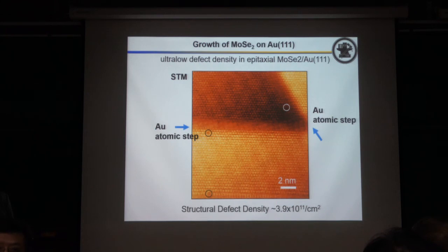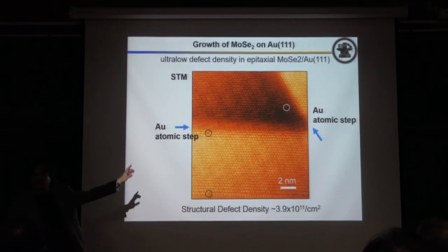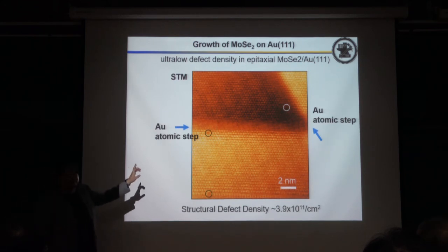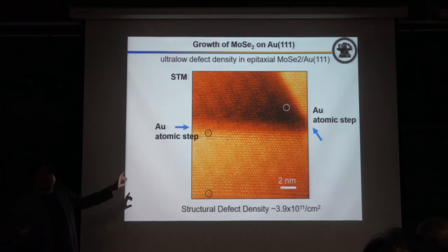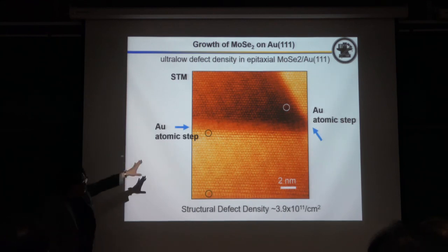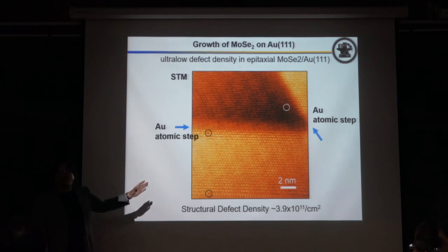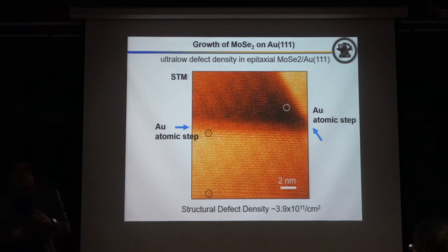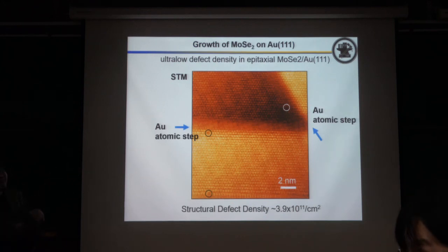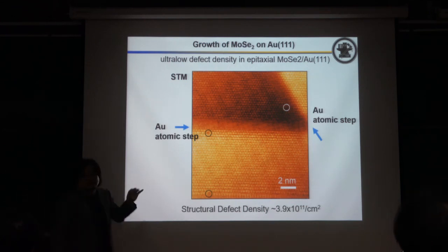I thought the typical defect is the vacancy, right? But actually, sulfur or selenium vacancies cannot exist on the surface. They are always passivated by oxygen. But in this case, oxygen will not produce a band gap state, so it only has a little doping effect. So it is not very serious.